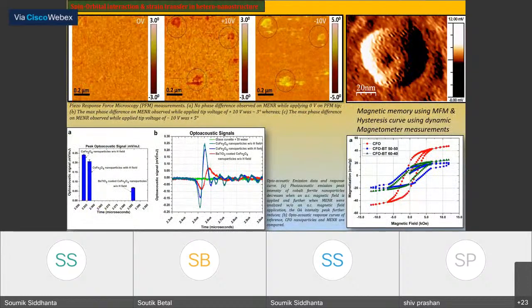Again, since I said that this was all in a DC magnetic field, right? But if we really need electric field generation by an AC magnetic field, there should be a fluctuating behavior of the shell. This can be seen here from the PFM measurement, where the atomic force microscope tip at 0 voltage shows some topography of these particles. But when the tip voltage was plus 10 volt, there is a phase change on these small nanostructures. And when we flip the electric field to minus 10 volt, we can see the switching behavior of the nanostructures, and the phase changes to the positive side.